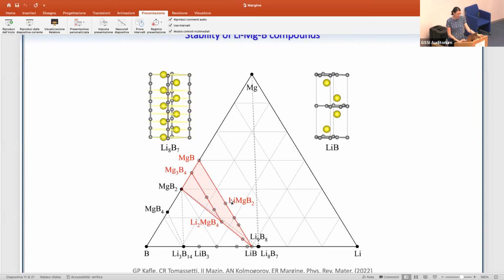By keeping monovalent lithium and divalent magnesium, we are ensuring that the boron sigma states are hole doped. This is one of the key features that we wanted to maintain, because this is what is known to be beneficial in MgB2 superconductors.